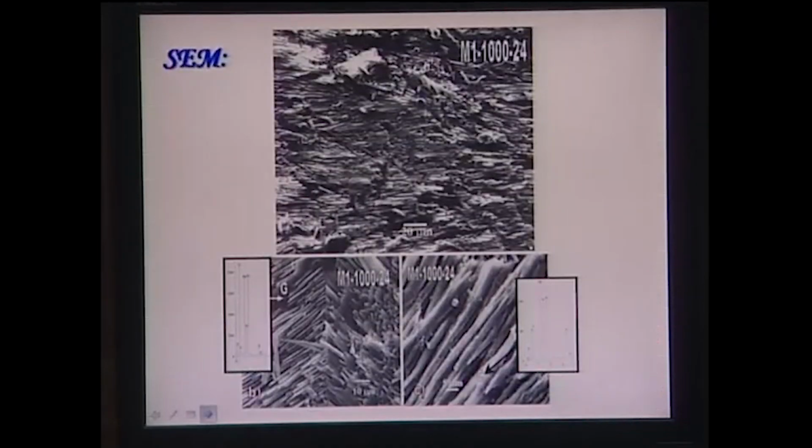Now for these materials which are developed by varying the fluorine content in the glass ceramics, an important thing that you can notice is the glass domain and the crystal domain, and in each individual crystal domain the crystals are oriented differently. They are much like rod-like structures, and these rods experience anisotropic growth, and anisotropic growth has been shown here also.